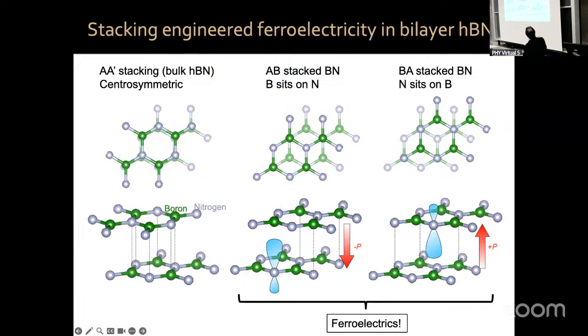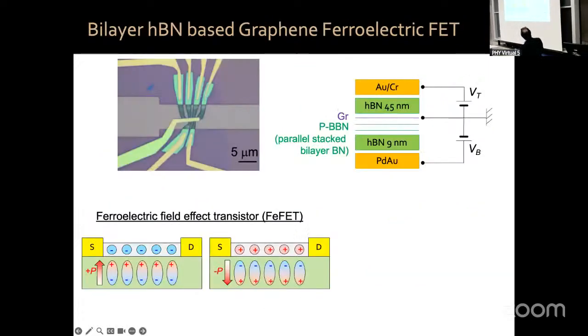And it turns out these two configurations have electric dipole moments which are opposite to each other. So if you have a way of switching between these two, you have a switchable ferroelectric, something with an electric dipole moment that you can switch. And indeed, that's what we did. We made devices where we have this parallel stacked bilayer boron nitride.